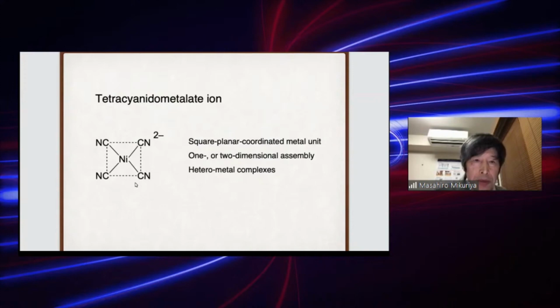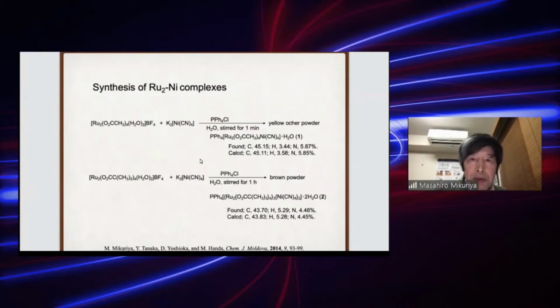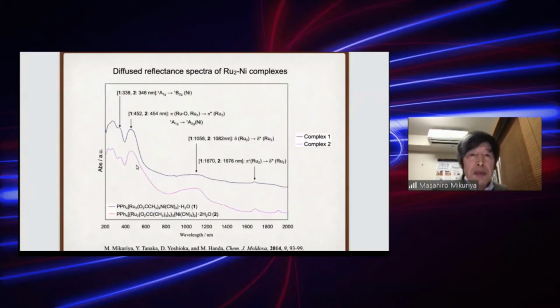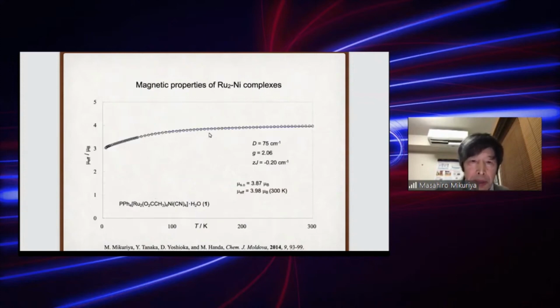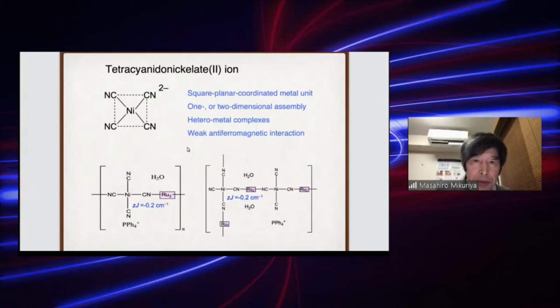So next we used tetracyanometallate ion, and first we used nickel to make mixed metal species, and we could see the presence of nickel linkers with ruthenium species in the diffuse reflectance spectra. And in this system we could obtain again very weak interaction, and we could not get a single crystal for this system, and we suppose our compound has this kind of structure, and we can observe very weak antiferromagnetic interaction between ruthenium spins.